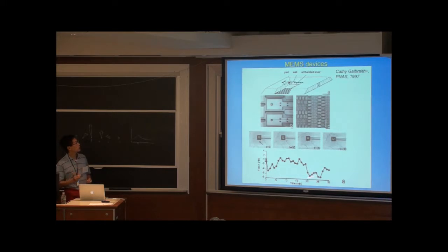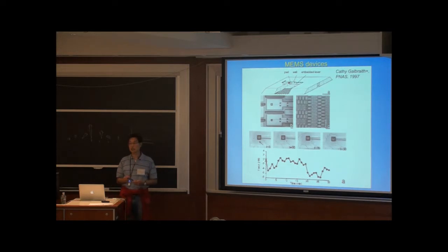So this is an alternative approach that really was started by Mike Sheets. He said, I don't like this polyacrylamide gel method. It's sort of continuous, and you might understand why it's a little bit uncomfortable when you're getting your data. So he said, why don't we develop a device, a silicon device, silicon, not silicone, okay? A silicon device that we fabricate so that we can put cells on top of it. And then these devices, these MEMS devices, are designed to measure forces.